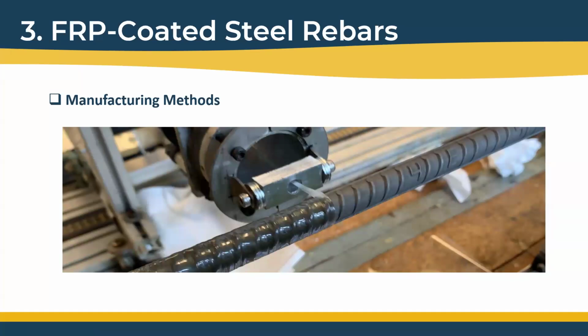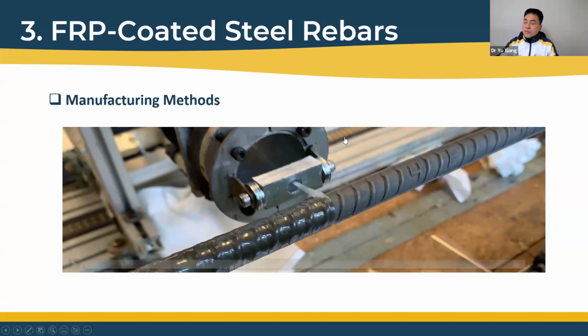FRP coating is applied for steel rebars by wrapping instead of heating or chemical treatment—how to ensure the coating sticks on the steel bars? For the manufacturing of one steel rebar, we actually have many steps. The first step is pre-treatment of the core steel rebar, like oil removal and descaling. As for hardening the coating layer, because we want to reduce energy consumption, this technology does not need additional heating—we just put them at room temperature for several hours, and then it will harden.